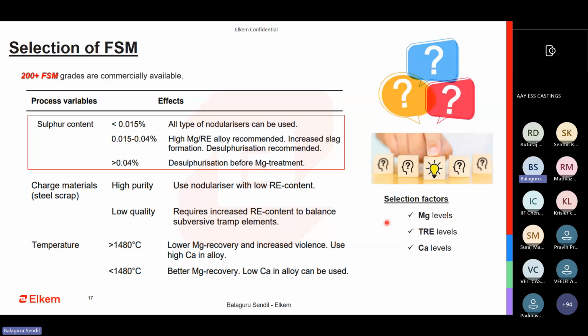This rare earth is directly related to your scrap quality. What do I mean by that? How much trace element is present in your metal, which you know from your base metal? If your base metal has a higher amount of trace elements, or you take a management decision to purchase scrap with slightly higher trace elements for commercial reasons, these elements like titanium or boron or arsenic or lead are going to cause certain problems in my microstructure. How do I neutralize it? In that case, I can go for an FSM with rare earth in it, which is going to primarily solve the problem of having tramp elements from the charge.